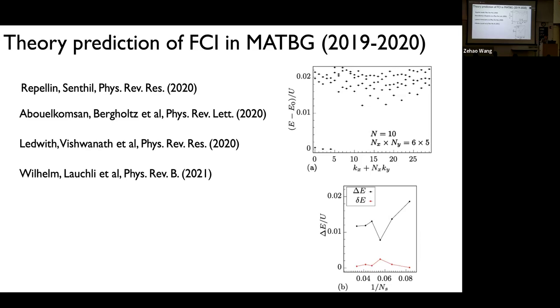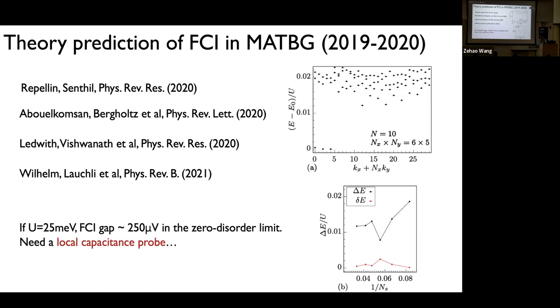It's about 1%. Now, the knowledge I had at that time is, I showed you in the previous slide, U is about 25 millielectron volt. Then what that means is that if you have a perfectly clean sample, so in the zero disorder limit, then the gap for the FCI, at least in this case for 1/3, should be 250 microvolt. If you convert to temperature, it's a few Kelvin, but in real life, you always have a lot of disorder. And the disorder is actually even more complicated here.